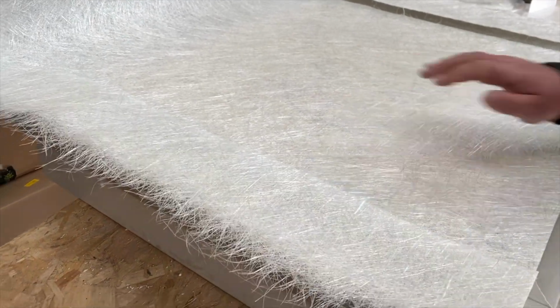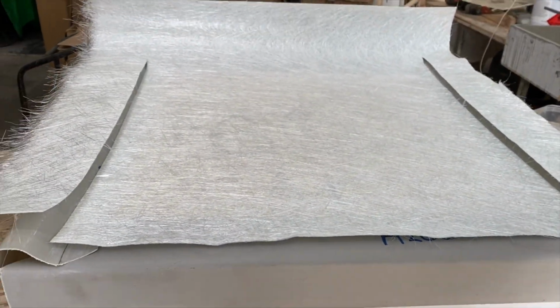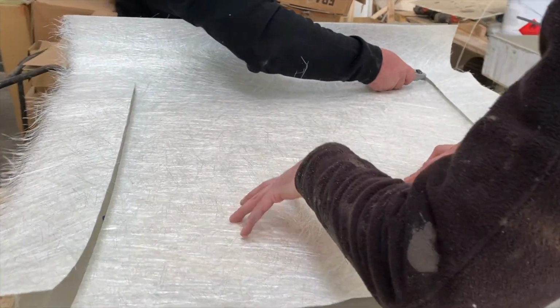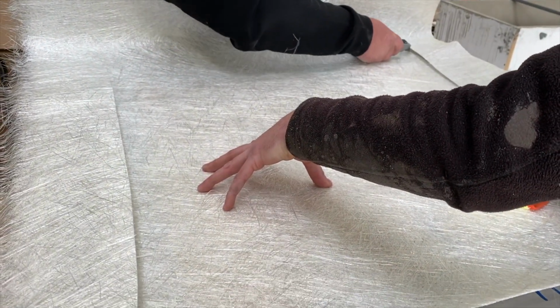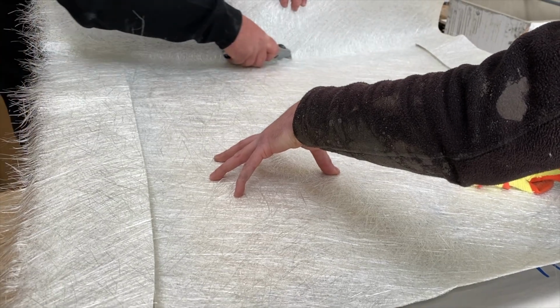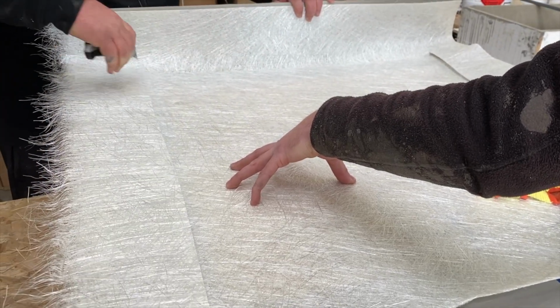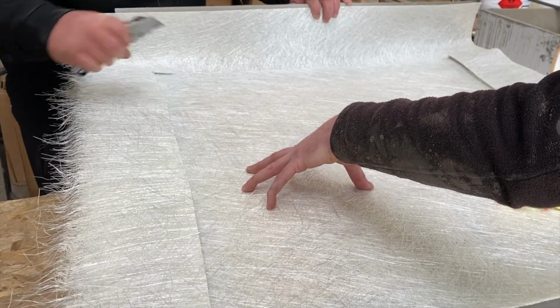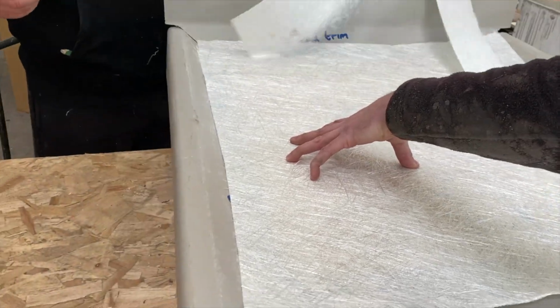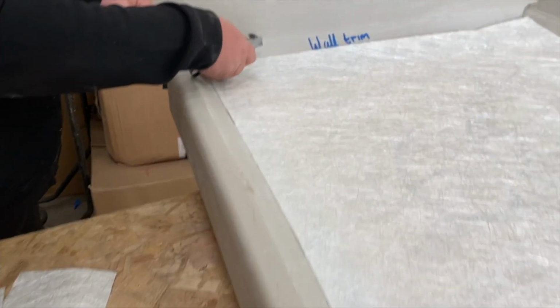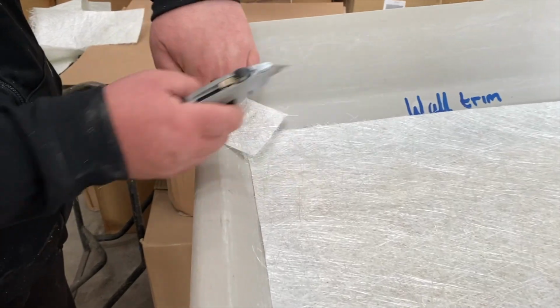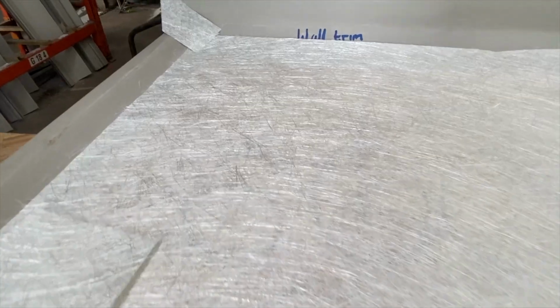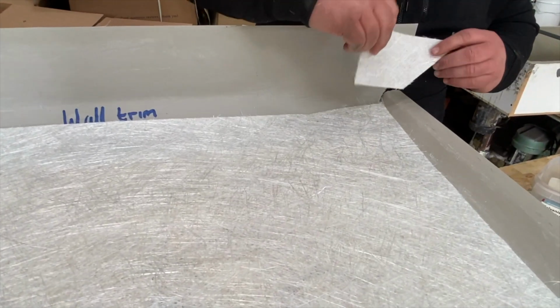In the example we're using here, we're using 600 gram chop strand matting. This is typically seen as industry standard for most fiberglass roofs. When joining or intending to join sections of glass fiber matting, it's a good idea to aim for a 50 to 100 millimeter overlap to ensure a seamless barrier is created in the laminate. So it's a good idea to have all of these sections of matting pre-prepared in advance.